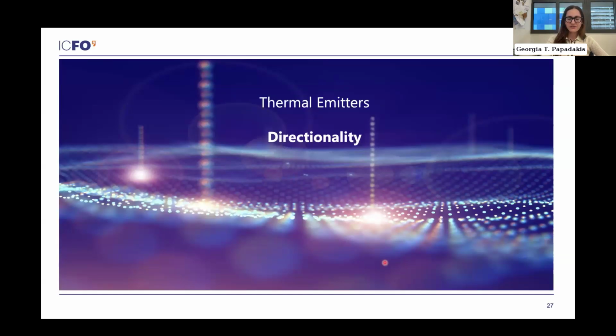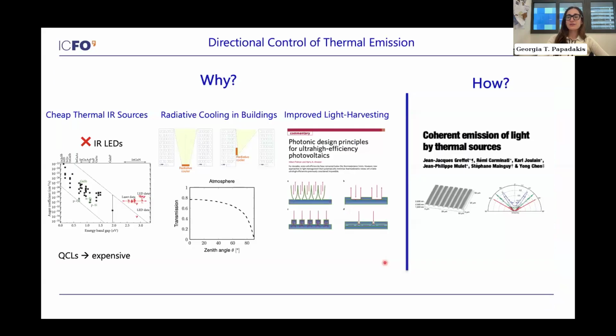Something else that is really interesting to us for application purposes specifically is directionality. So it's really important, yet really difficult to confine thermally generated light into a very narrow spatial regime. However, it's very important. And here I'm only listing 3 reasons why it's very important. One of them being to build cheap thermal sources. So in the mid-IR, the only light source we have in the form of a laser is a QCL laser, which is very expensive. We don't have LEDs that operate in the IR, and the reason for that is that semiconductors have this non-radiative recombination that becomes very, very large and parasitic at low photon energy, so in the mid-IR range.